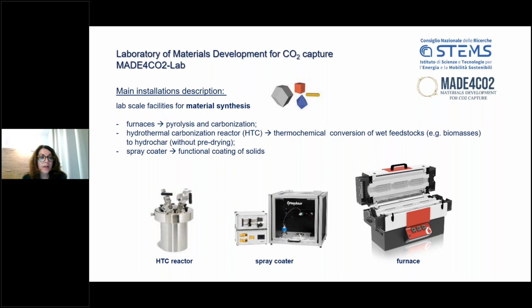We will have lab-scale facilities for material synthesis, including a furnace for pyrolysis and carbonization of raw materials, for instance, biomasses, and a hydrothermal carbonization reactor to obtain a thermochemical conversion of wet feedstocks. This HTC reactor will enable us to use wet feedstocks without the thermal treatment needed for water elimination. A spray coater for functional coating of solids.